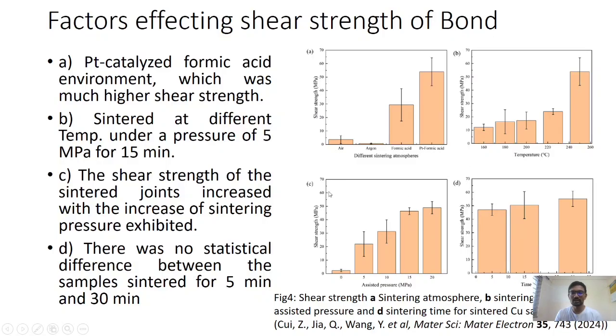But increasing the temperature beyond 250 degrees is very harmful for our electronic devices, and it decreases our thermal stability. So to compensate for that, we increase our pressure. The third parameter is pressure. When we increase the pressure from 5 megapascal to 10 megapascal, the strength at 5 megapascal is only 20 megapascal, but by applying 10 megapascal pressure, we get a shear strength of 35 megapascal.